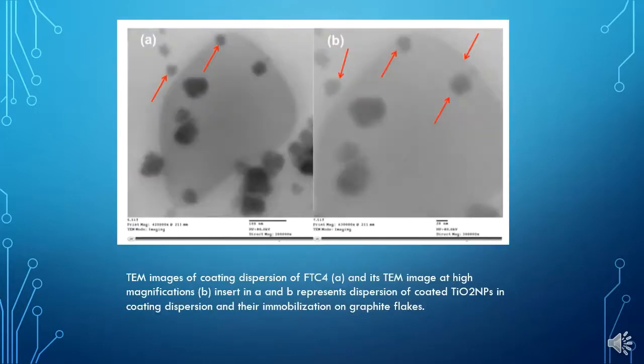figure. The figure represents the dispersion and decoration of the TiO2 nanoparticles on graphite flakes. Figure A shows the TEM images of coating dispersion of FTC4 and its TEM image at high magnifications, while the figure B represents dispersion of coated TiO2 nanoparticles in coating dispersion and their immobilization on graphite flakes. Now for some SEM images.